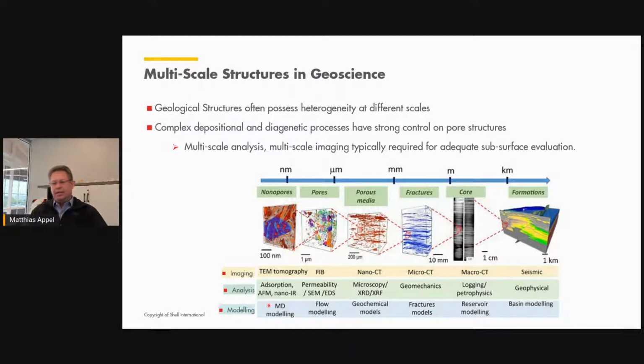Yeah, so in nanopores, we typically need tomography, microscopy with very, very high resolution, SEM and TEM. The physical measurement is more adsorption, atomic force microscopy, nano infrared spectroscopy. Modeling is typically at the small length scale, so molecular dynamics modeling is sufficient. Then we are getting into pores, where we have focused ion beam scanning electron microscopy, making measurements. And the impact here is primarily on the permeability.